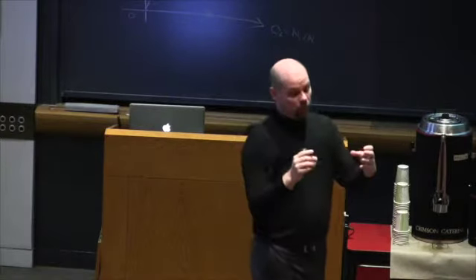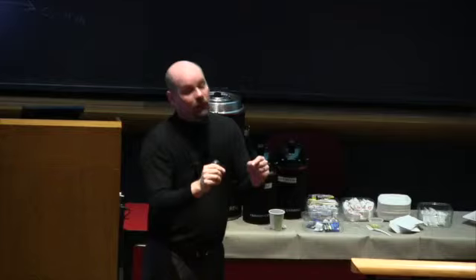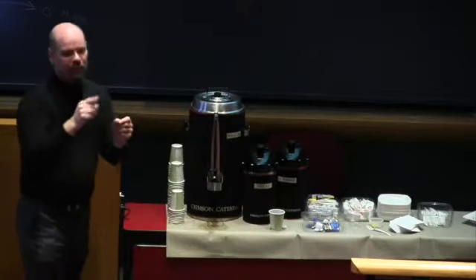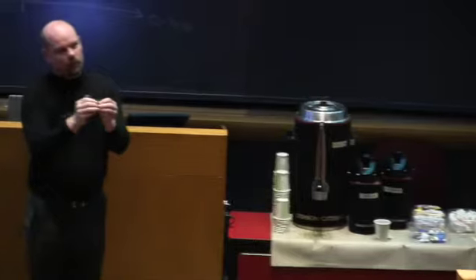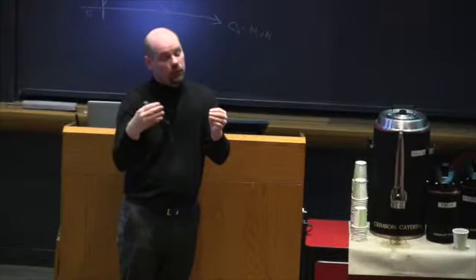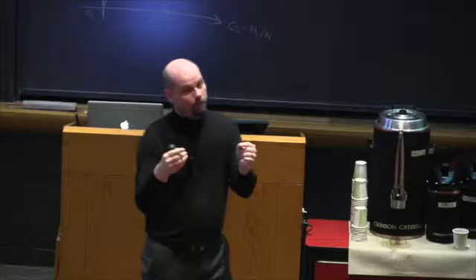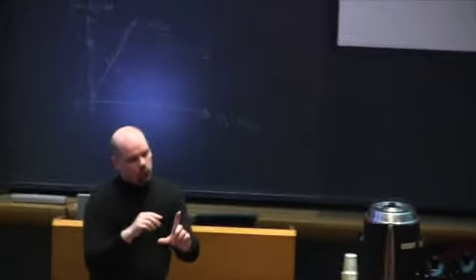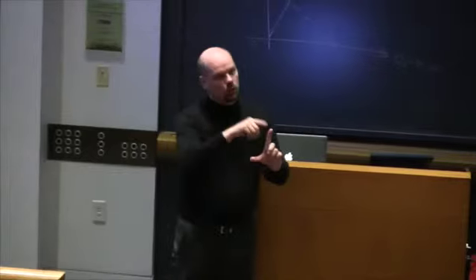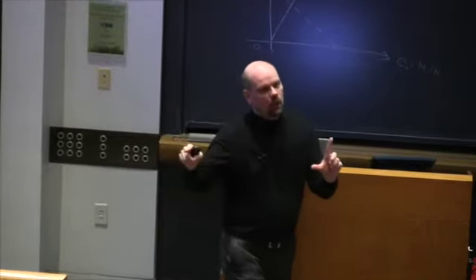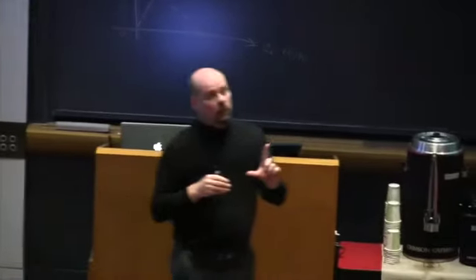So the thing to do would be to look at how the intensity develops. This intensity can depend, I think, on the coupling of the X-ray to the electron-hole continuum. So one would have to do an absolute measurement of the X-ray absorption intensity as a function of doping, which nobody has done, and compare that to some theory, your theory, to see how a coupling to the electron-hole excitations renormalizes that intensity and redistributes it a little bit, but that's not a big effect.